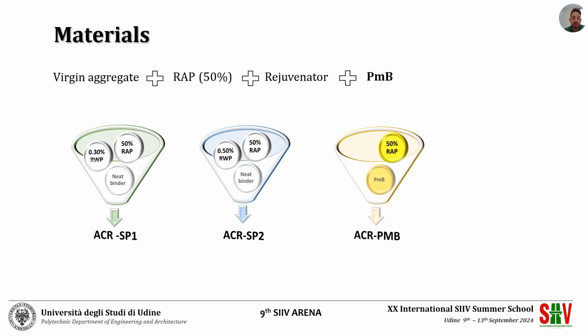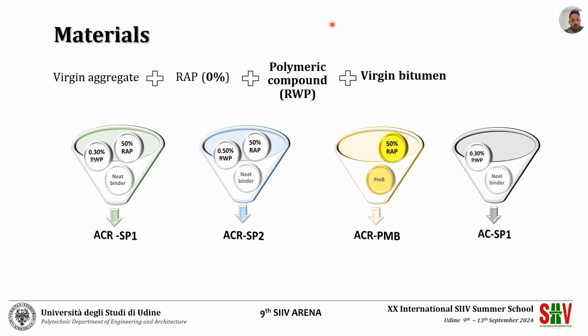Additionally, a set of control mixtures with PMB instead of neat binder and polymeric compound was investigated to compare the effect of polymer modification via the hybrid method with those of standard modification via the wet method. Finally, another control mixture containing 0.3% of polymeric compound and only virgin aggregate AC-SP1 was tested to isolate the influence of RAP.